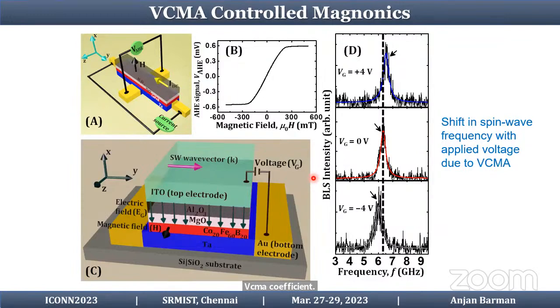But here we want to develop a new kind of system, that is a voltage-controlled magnonic nanochannel or voltage-controlled magnonic crystal, by patterning these electrodes. So what we did is, first we have a continuous electrode, and we have this cobalt iron boron and MgO heterostructure, and there is an aluminum oxide structure, and by using these two gates, we apply electric fields.